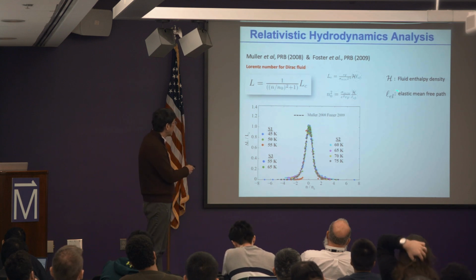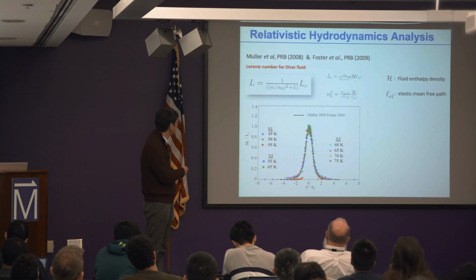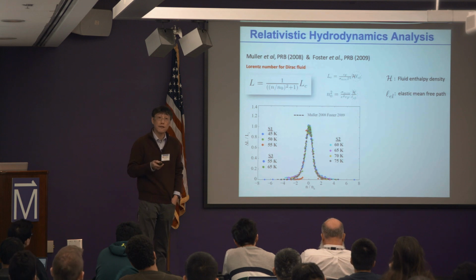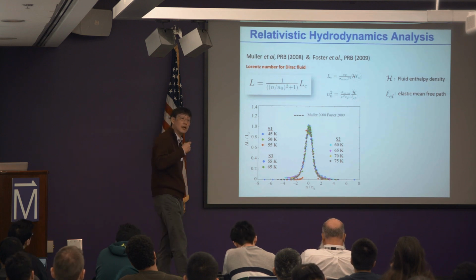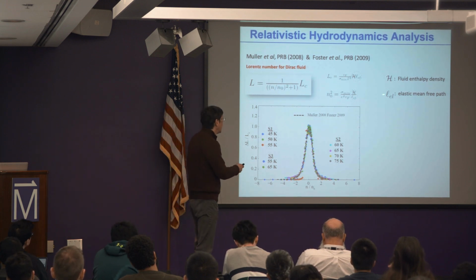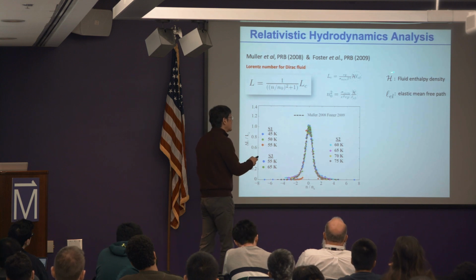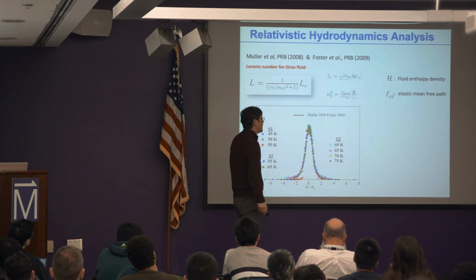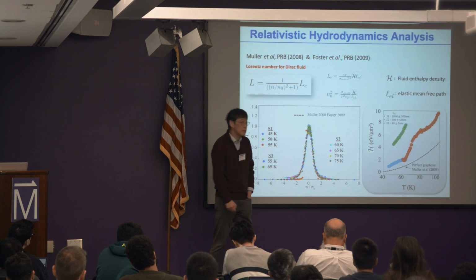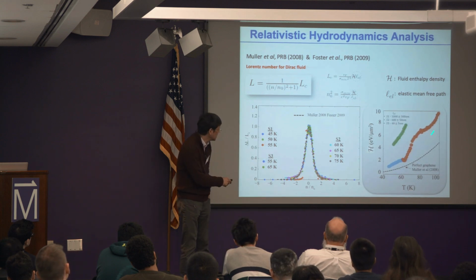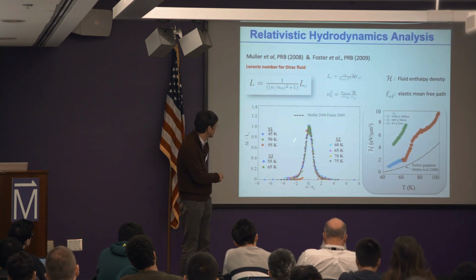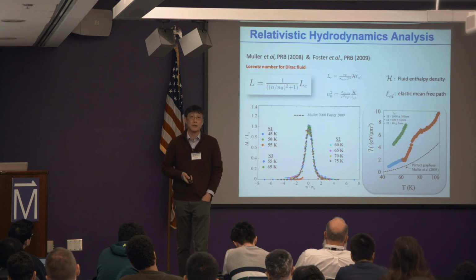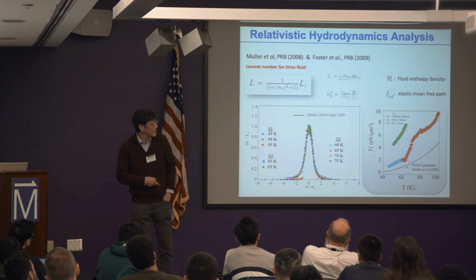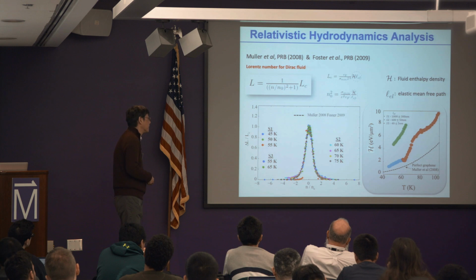Now, the scattering length, the elastic mean free path, is not actually a fitting parameter. In fact, we can extract it from our electrical conductivity measurement. And from there, in principle, we can extract the enthalpy densities in this system. If you plot it out, the enthalpy density increases with temperature in the system that we measured with various different types of disorder.